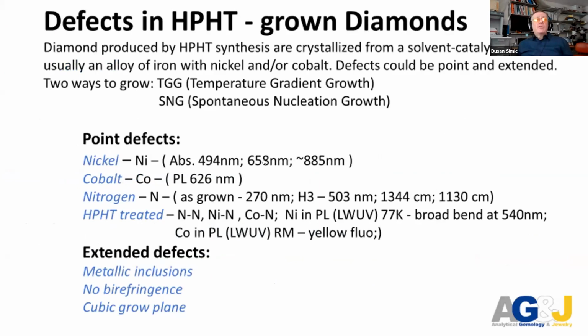Defects in HPHT growth diamonds are mostly related to the catalyst. They allow the diamond to grow at lower temperature and lower pressure. This is nickel, cobalt, nitrogen; boron is not here, but it is very popular now as a catalyst, you know. And what is interesting with HPHT grown diamonds is that there is no birefringence, there is no brown color, and HPHT treatments could be used, and I will show later how and what changes could happen during treatment.